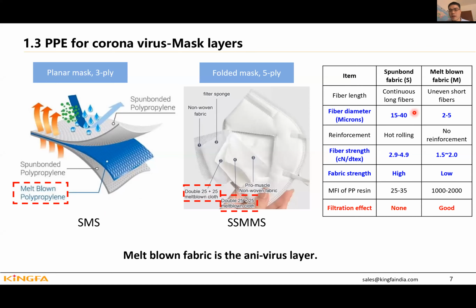Here is a comparison of these 2 fabrics. The spun-bond is very strong, and it's not easy to break. It has good strength, but the filtration effect is not good. And for the melt-blown fabric, the fiber diameter is only 2 to 5 microns. The filtration effect is very good, but it's very easy to break. So we put it in the middle layer. So in this mask, the melt-blown fabric can capture the virus and protect ourselves.